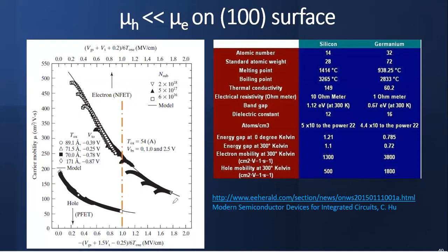You could look at this universal curve from Takagi. You could see that at the one, I took a typical value of one, this one megavolt per centimeter. And here you can see the electron mobility is 250, and the hole is like 60. So it's 4 times less, and that's a problem. So what do we do?